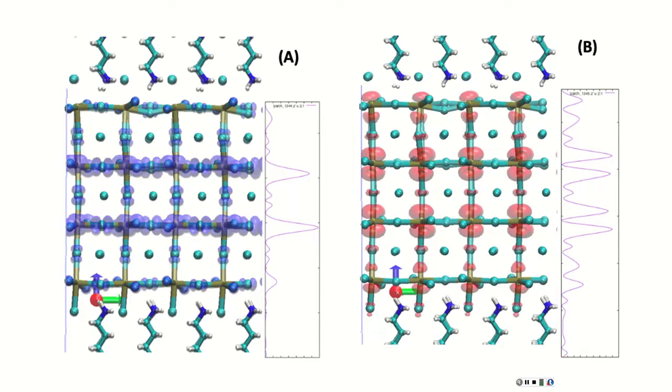Three-dimensional. Is it like we have top and bottom, or is it periodic? Thin film has two-dimensional features, but it is represented. But anyway, here the surface is completely isolated by this ligand, right? And they do not contribute to your HOMO-LUMO gap, while the other ones have these orbitals of top and bottom completely occupied, and this probably caused this difference in the band gap, right? So the organic layer works as an insulator, and the inorganic does not. Yeah. Okay. Let's thank David once again.